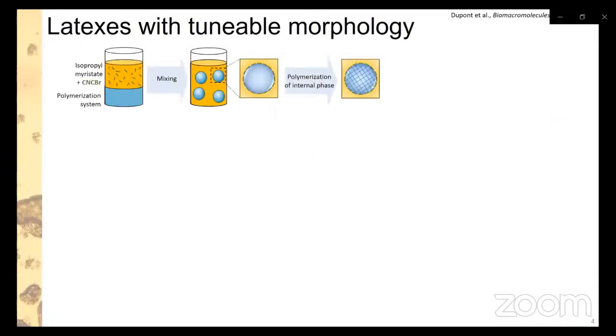The second subject we were interested in was the polymerization of the dispersed phase this time. Similarly to previously, we dispersed the hydrophobic CNC into an organic medium, which was this time neutral, isopropyl myristate, an oil from the cosmetic industry. And we dispersed a polymerization system inside. So we obtained the inverted emulsion stabilized by the CNC, and we were able to polymerize these beads.